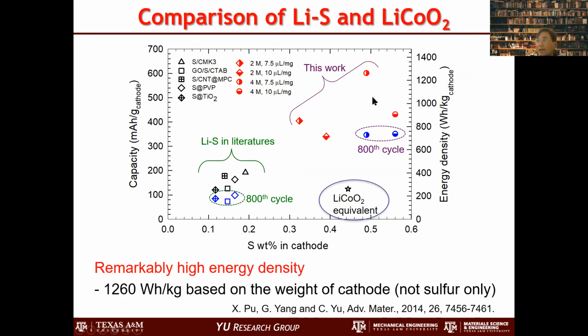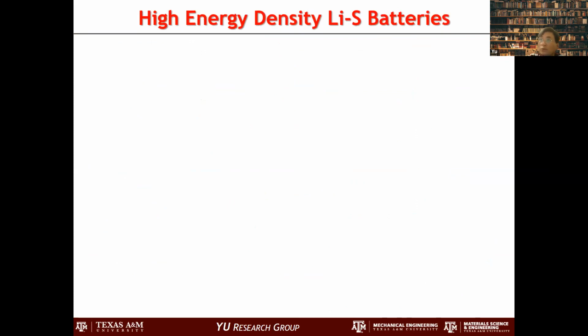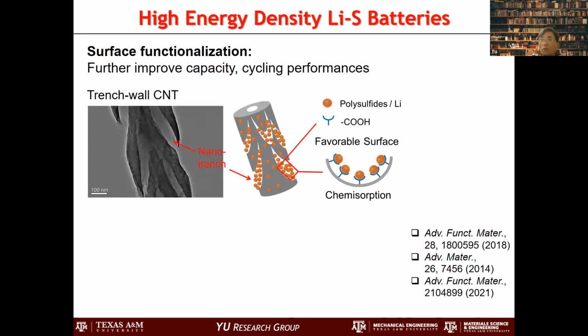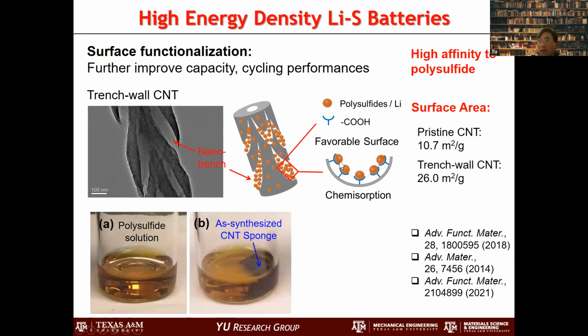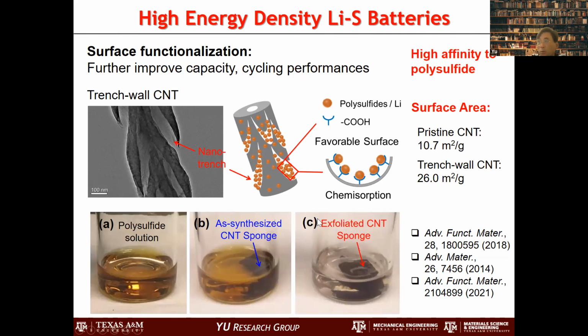It's fantastic, and we have been working on this technology for a long period of time. We have a lot more development. One of the techniques we're using here is that the carbon nanotube can be functionalized by making a kind of trench. We make multiple nanotubes and create this kind of trench, and then we put on carboxyl and hydroxyl groups, which attract the polysulfide, so we have pretty good affinity. The polysulfide is absorbed when we put the carbon nanotube sponge in, and the solution becomes transparent from the initial color. They basically absorb all the polysulfide, and then we can avoid the polysulfide shuttle in this case.